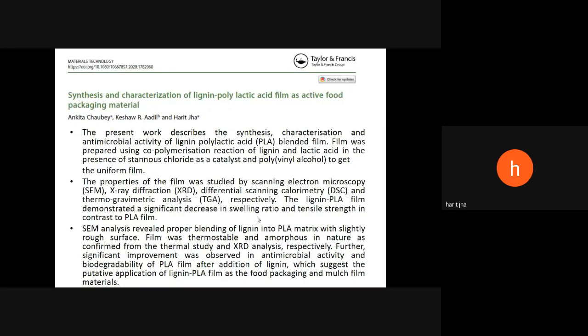SEM analysis revealed proper blending of lignin into the PLA matrix with a slightly rough surface. The film was thermostable and amorphous in nature, as confirmed from the thermal study and XRD. Further, significant improvement was observed in antimicrobial activity and biodegradability of the PLA film after the addition of lignin, which suggests its putative application as food packaging and mulch film material.